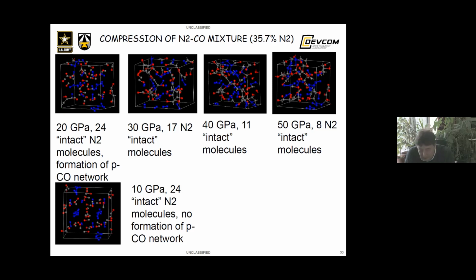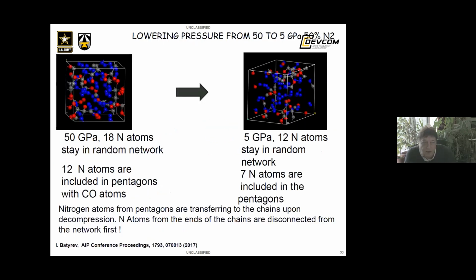The network consists of chains and rings. Upon decompression from 50 GPa to 5 GPa, seven nitrogen atoms still remain in the rings. CO molecules are lowering the transition pressure to incorporate nitrogen atoms in the network, and upon decompression, the presence of CO molecules in the mixture stabilized the network structure. We found that the weakest links to be first disconnected from the network are the ends of the chains. Rings split and form chains. Atoms from the ends of the chains get disconnected first.